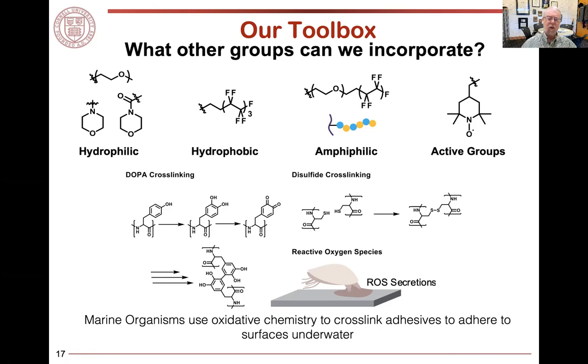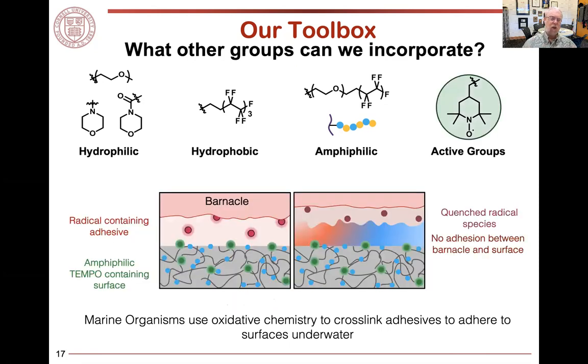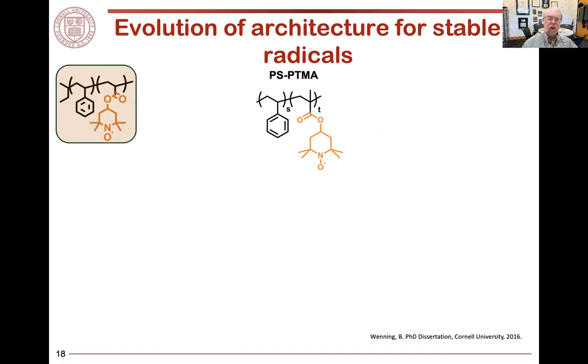And if we can prevent that, inhibit it, we will always have a soft, uncured adhesive that motion through the water may be able to then dislodge the hard fouler. And so our goal then, as you can see in this figure, is that when the barnacle tries to put down its radical containing adhesive, our TEMPO units interfere with that, and we form a very thin layer where attachment is quite weak. Now, we have studied TEMPO in a wide variety of polymer architectures.